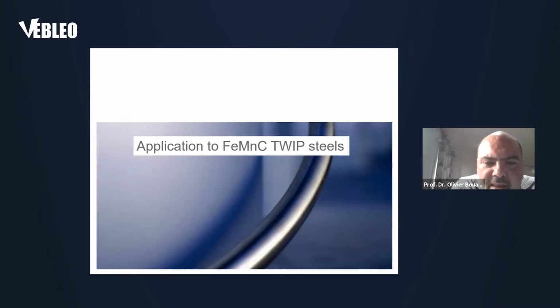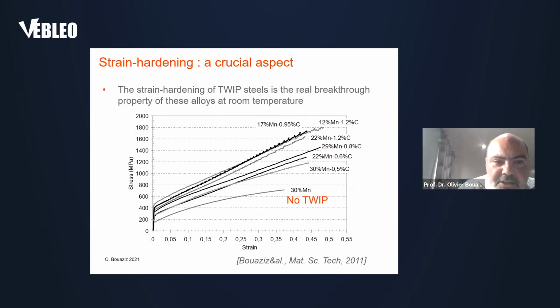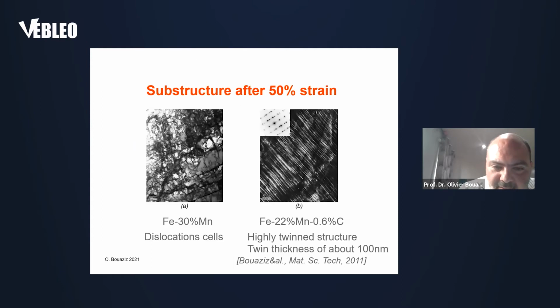At first, I want to show you an application of TWIP steel. As you can see here, the strain hardening of TWIP steel is very impressive. It's a real breakthrough in advanced high strength steels. Why is the strain hardening so high? It is because by deformation the alloy twins. As you can see here, when there is no twin, you have cell formation, as usually observed. But in the case of twinning at room temperature, you have a nanostructuration of the material by a lot of twinning. And what we have shown in different papers is that the properties are controlled by the interspacing between twins.